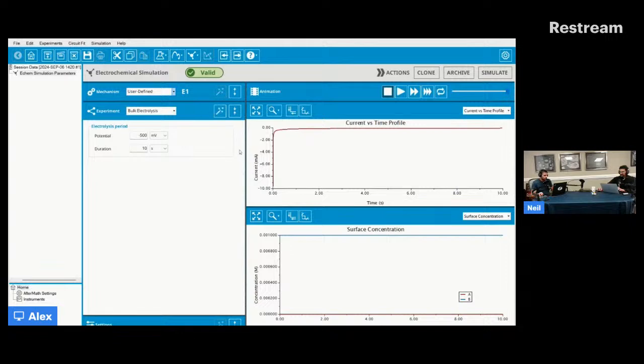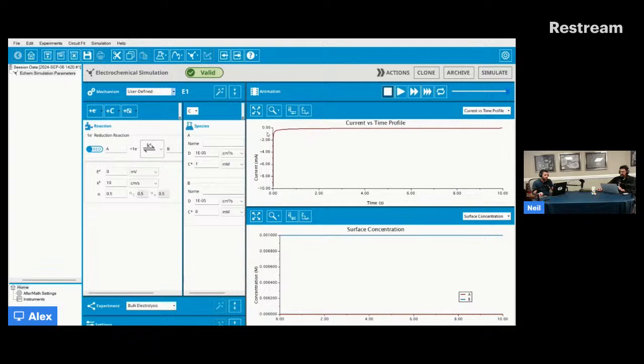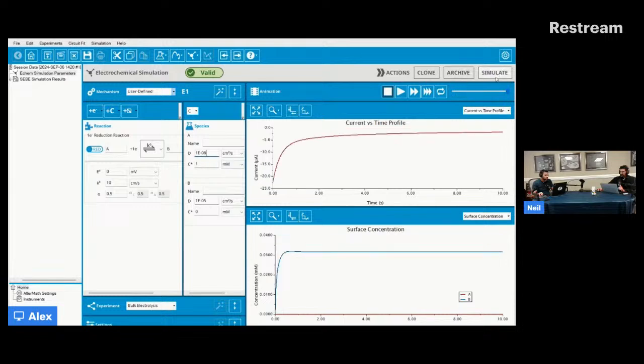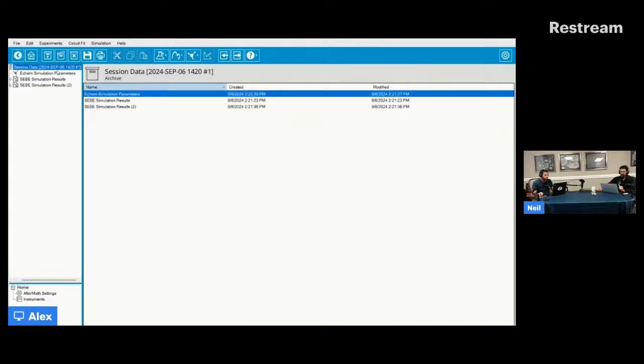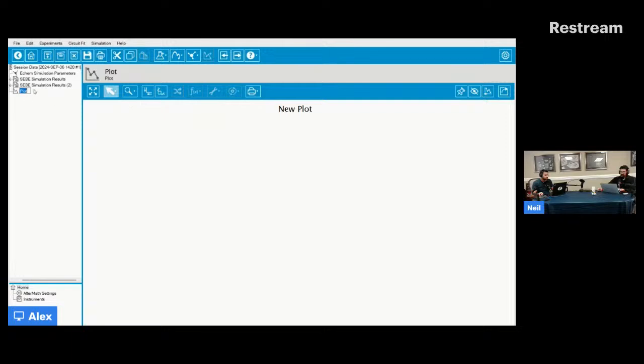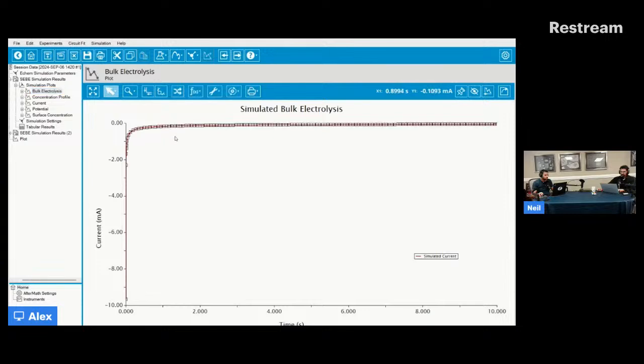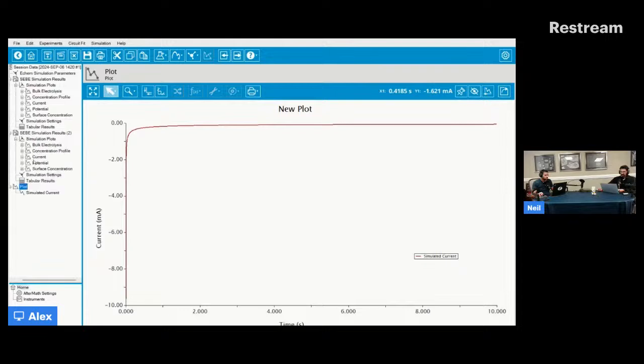So we'll do this reduction reaction. We're getting milliamps of current. This is going to be just very regular. Now I'm going to change the diffusion coefficient. So let's say I'm in my hydrogel, so I'm much slower, very slow. If I simulate that, I get this. Now if I archive these two, I'm going to create a new plot. I'm going to take my normal one, and going to take my slow diffusion coefficient.